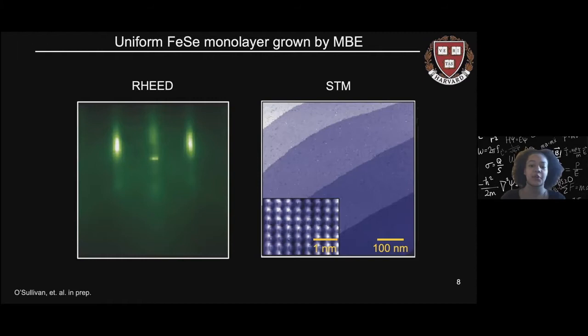We successfully grew a monolayer of iron selenide on bulk strontium titanate, as shown here, using molecular beam epitaxy. So here the diffraction pattern of our RHEED image shows that we had a successful monolayer growth, and our STM image shows that we have a clean, well-ordered atomic resolution monolayer and no bilayer.